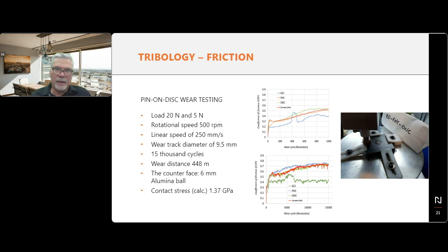Of course, it has a coefficient of friction that appears to be lower. And one of the reasons that really explains that is that, as such, gray cast iron is considered a self-lubricating material. What happens is that due to the presence of graphite flakes, graphite will form what we call a tribofilm, a very fine film between the two contact surfaces that will lubricate the pin. So you're trying to wear out a surface, but you are actually riding on lubricated surfaces. And this is why apparently it has a lower coefficient of friction, but it's not necessarily better for braking.